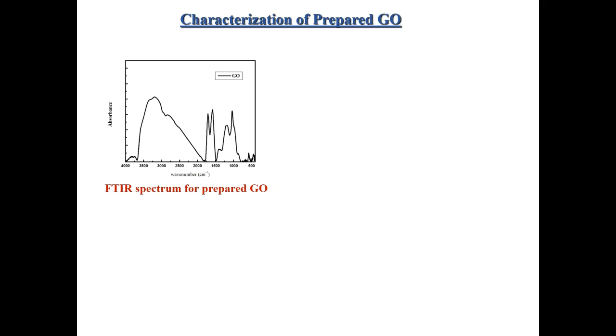For graphene oxide, FTIR spectra show the absorption bands of the C=O stretch of the carboxylic group and the C=C of graphene sheets at 1713 and 1575 cm-1. In addition, an absorption band appeared at 1421 cm-1, attributed to the OH functional group. C-O-C stretching and C-O vibrations could also be due to the carboxylic acid and carbonyl groups located at the edges of graphene oxide, at the two absorption bands around 1218 cm-1 and 1049 cm-1.